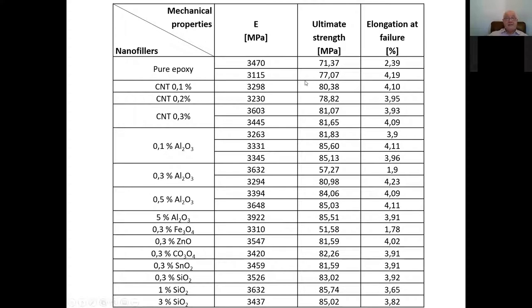However, the problem of mixing nanopowders and carbon nanotubes, all kinds of nanofillers, into the epoxy is not simple, because presumably you are going to get some improvement of properties, and you get a certain improvement of properties from the point of view of strength, from the point of view of stiffness, but elongation at failure, so toughness by itself, is not convincing from the point of view of value.